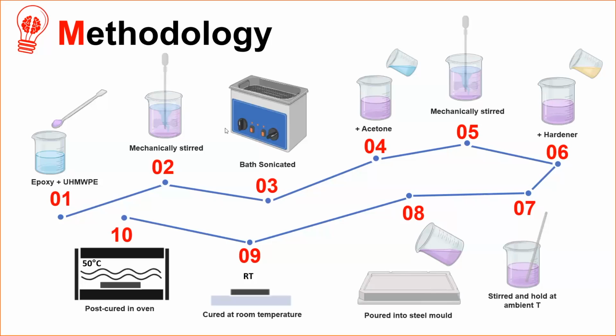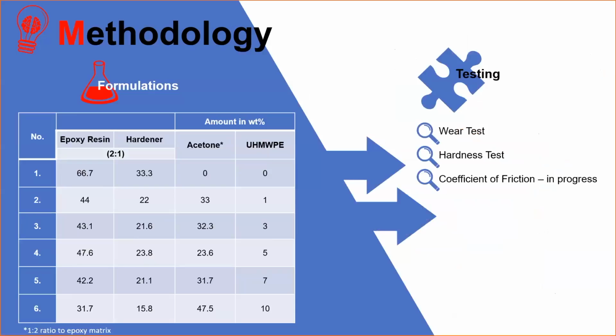Okay, this is just the summary of the method. Okay, this is the final formulation. There is only one variable, which is the amount of ultra-high molecular weight PE, varied at 1, 3, 5, 7, and 10%. The optimal ratio of acetone was kept constant at a 1:2 ratio of acetone to epoxy resin. The testing involved for this part are wear test, hardness, and coefficient of friction test, which is still in progress.